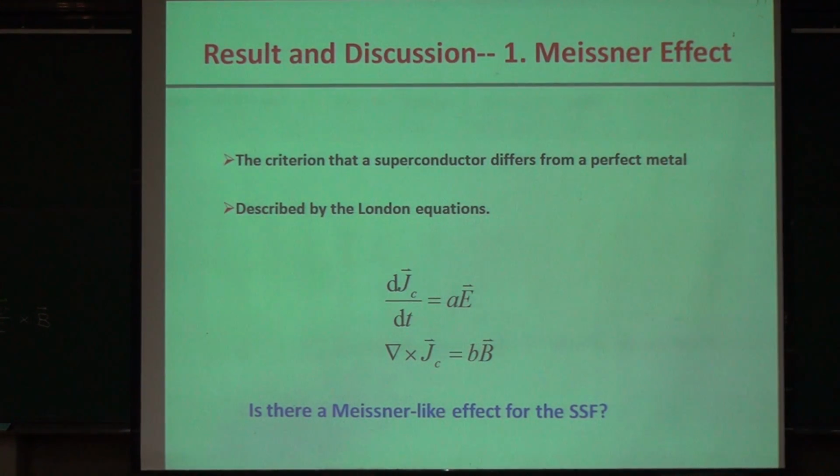So far I tried to introduce this concept of spin superconductor. Basically, if you have bosons with non-zero spin, spin 1 or spin 2, whatever, then if you make a condensation of these bosons, it is a spin superfluid, a spin superconductor state. And we propose that ferromagnetic graphene is a possible candidate to have this spin-1 boson system, basically spin-1 triplet excitons.